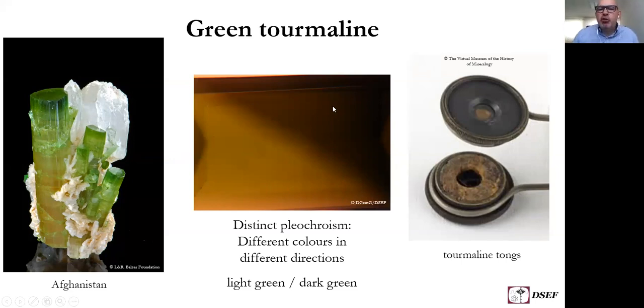This is very distinct in tourmaline, and because of that, and because tourmaline in a certain direction of the crystal, I'll show you that, can actually produce plane polarized light, tourmaline was used very early as a type of polariscope. From two tourmaline prisms cut parallel to the optic axis, mounted in a piece of cork, which is then mounted in rotatable brass discs, you were able to separate optically isotropic from optically anisotropic stones. And for this, tourmaline crystals were used.